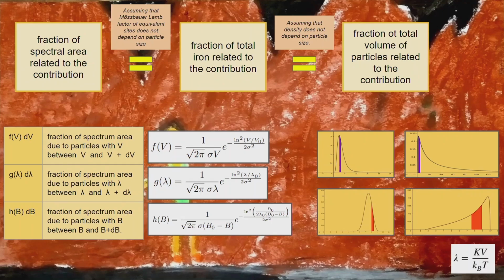So what next? We always assume that the fraction of spectral area is related with the fraction of total iron in the contribution, and that is related with the fraction of total volume of particles related to the contribution. Okay.